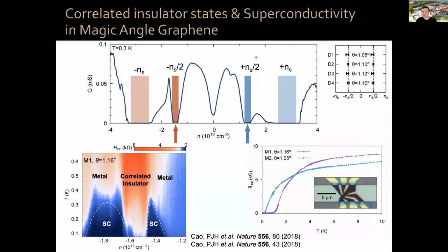And this correlated insulator behavior only occurs in a narrow angular range around 1.1 degrees, okay? Something like between 1 and 1.2 degrees, if you push me, 0.95 and 1.25 degrees. Now we were looking back then for insulator states, but not of this type actually. And then the biggest surprise came when we doped around these correlated insulator states and we saw superconducting domes, okay?